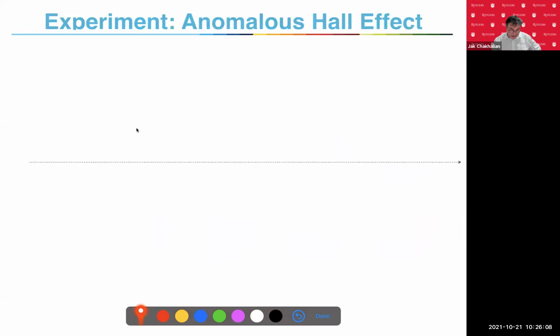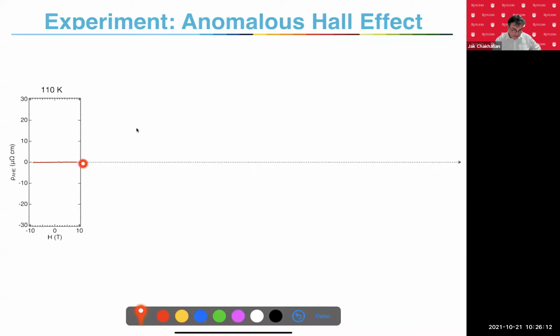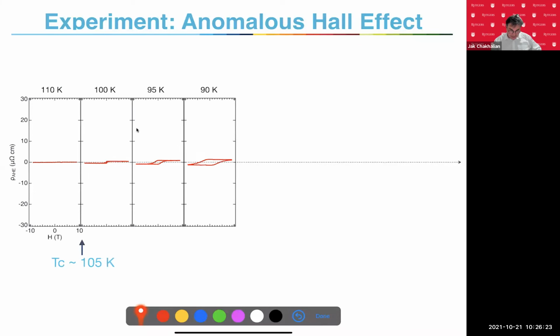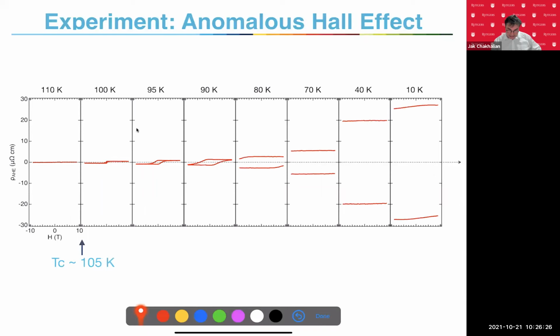And so I want to show you the experimental result to finish my talk. This is where the material is non-magnetic, so the Weyl nodes are not appearing here. It's just a control check. This is the anomalous Hall effect resistivity here. And then it becomes magnetic, and you can clearly see there is a beautiful anomalous Hall effect, a hysteresis, even at zero magnetic field. So at zero magnetic field, you can see this hysteresis is really as if you had a magnetic material, like a ferromagnet.